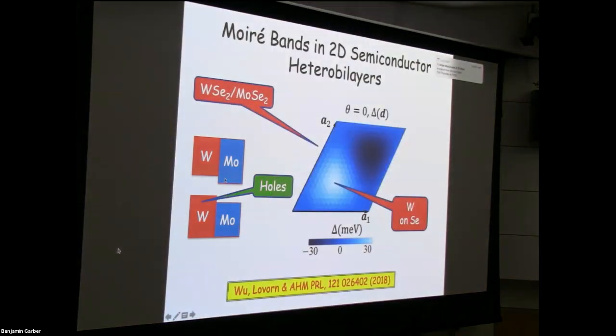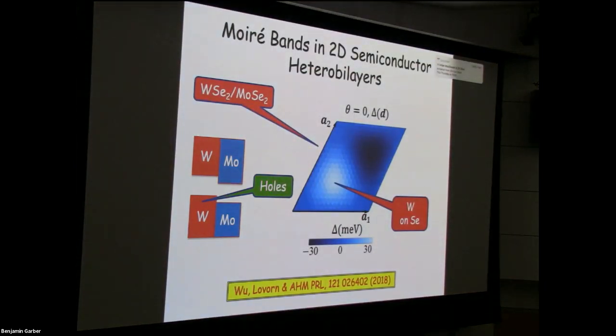And so if you remove a few electrons from the valence band, if you make a few holes, you can see that they're energetically preferred to be in the tungsten by an energy amount which is a few tenths of an electron volt, and that's a large energy as far as what I'm talking about is concerned. So that means that holes exist in the tungsten diselenide material. And we know that there's basically two states for every momentum. And now I'm slipping into semiconductor physics jargon by measuring momentum relative to the Brillouin zone corner when I say those words.